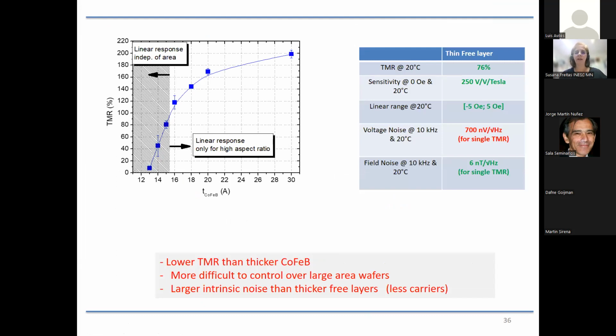What is the drawback here? If we measure the magnetoresistance, so TMR, tunneling magnetoresistance, as a function of the free layer thickness, here the normal thickness is 3 nanometers, so 30 angstrom. Here we have the maximum, 200%, typical. But then if you start to reduce, and you start to have a very nice linear response below 15 angstrom of cobalt iron boron, then you start also to reduce the TMR ratio. So you're losing signal. Although you gain in noise, you also lose signal.